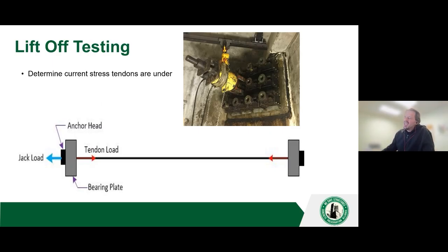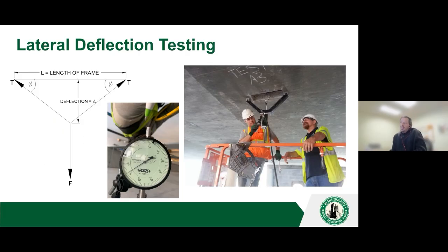Just briefly, just know that these tests do exist. It's not common. One is lift-off testing. It's taking a jack, putting it on the end of the anchor if the tail of the tendon is long enough, and then putting some tension on it to see what the in situ stress of that strand is. And then lateral deflection testing. We'll go to the bottom side of a drape of a tendon, open that up, and then put the frame, the jack, pull on it, and based off of that calculation, tell you what the in situ tension is of that strand. It's not common. I've only seen it a couple of times in my career. Just not that common.